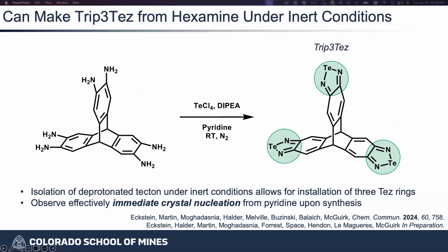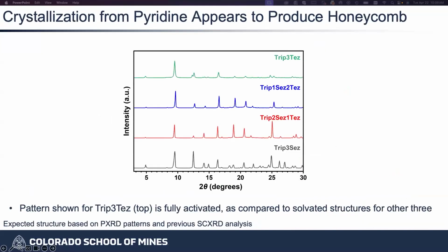And so this is where microED comes into the picture, is that when you make this molecule, it wants to assemble so badly that in the reaction mixture, it starts raining crystals. It immediately assembles as it's formed. But we're not controlling that, and so those crystals are really, really small. And so at first, we did what, if you don't want to drive Chris mad, you do: get your PXRD, make sure that your samples are actually nice and crystalline.